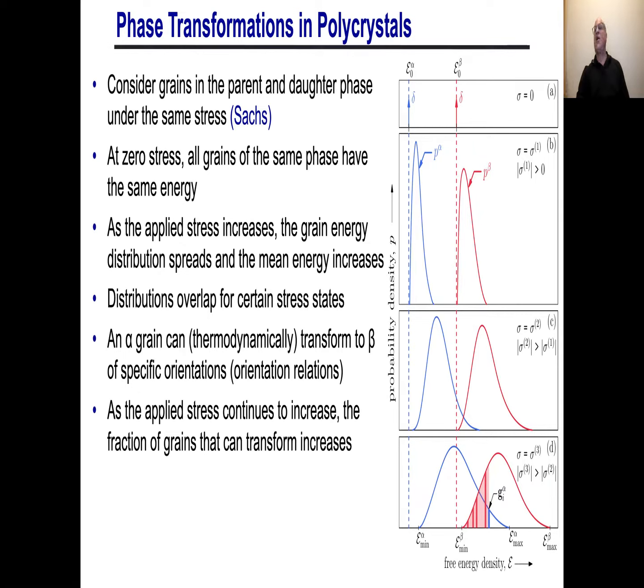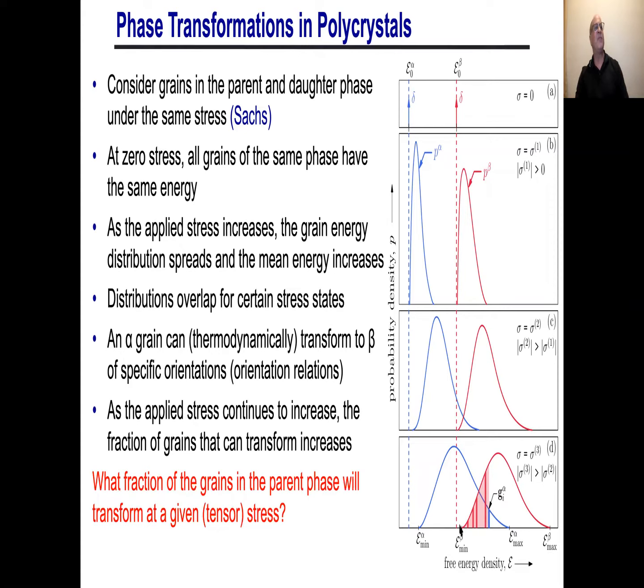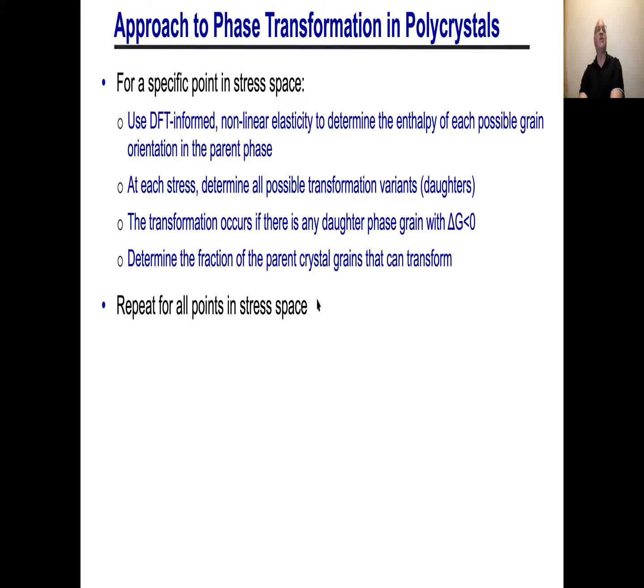Okay, so now as I increase the stress, the overall stress level, you get more and more overlap, and therefore more and more alpha grains will transform to beta. So we can look at that. We can ask the question, what fraction of the grains in the parent phase, a polycrystalline alpha material, transform to beta if I allow it to, for some arbitrary stress tensor? Okay? So I'll show you how to do that in a moment. I'll show you data in a moment.